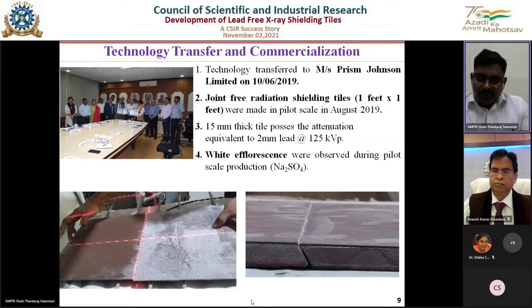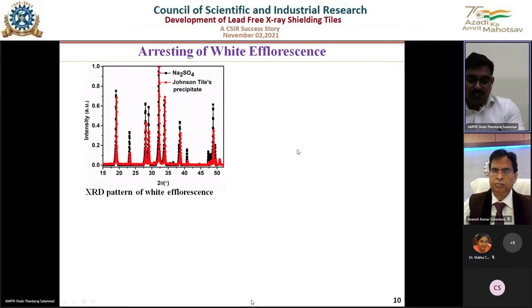But surprisingly, actually, the color of our tile is dark brown. But when we expose these tiles to the atmosphere, it becomes white. This is the pilot scale, where we made the tiles at the beginning of 2020 itself. But we see a lot of whiteness. Then we did a lot of R&D to find out. So we found out that the white powder is sodium sulfate.